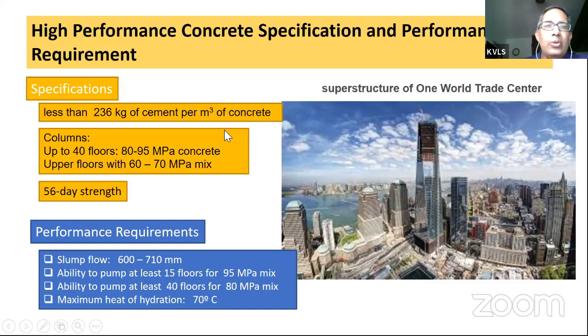Now, this is a very low number. Most of us who do use concrete and who have done concrete mix designs know that at the very least we use 300 kgs of cement per cubic meter. Otherwise, we use 350. 236 kgs of cement per cubic meter is a very low number, but this was specified. It was specified to the contractor that he or she could not use more than 236 kgs of cement per